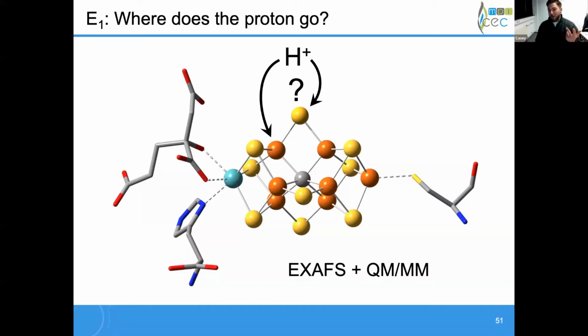I will say there are 3 nitrogenases that are known. They are very, very similar. There's molybdenum nitrogenase, there's vanadium nitrogenase, and there's an all iron nitrogenase. And those vary completely by what is here. Although the crystal structure of the iron nitrogenase isn't known, and a belt sulfide is replaced by a carbonate in vanadium nitrogenase, they're assumed to be otherwise very, very similar clusters. But the molybdenum nitrogenase is, by expression in organisms, always preferred. All organisms that fix nitrogen express molybdenum nitrogenase. Some, when they can't get enough molybdenum, can also produce vanadium nitrogenase or iron nitrogenase, or maybe both of those, depending on what they can get, but it totally depends on the organism.